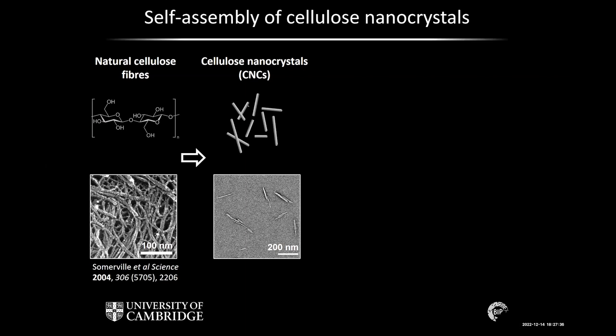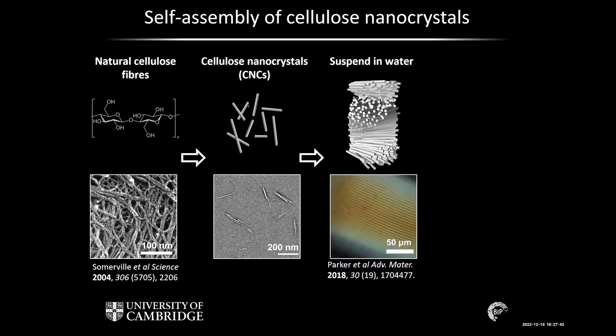Now, what we find is that these are stable in a colloidal suspension. And when we increase the concentration of this suspension and really pack the CNCs together, they spontaneously assemble themselves into this helicoidal type structure, which was also introduced very nicely by Sylvia. So locally, the CNCs are aligned with each other, but the overall structure has a left-handed twist. It has a helix-like configuration. And actually, when we look at this liquid suspension under the optical microscope, we see this fingerprint-like pattern due to the periodicity, due to the regular patterning of the structure.